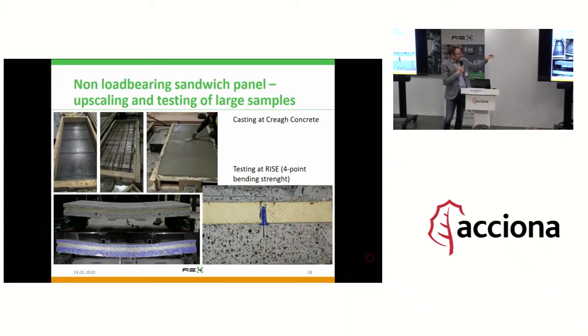And these are images from the preliminary upscaling at Creagh, in which we, from laboratory, made a first upscaling to produce test elements. And we tested this, for example, as you see down to the left, with 4-point bending strength, and supervised it with digital image correlation to see how the stress was distributed and how this element corresponded to this testing. And based on this, the real upscaling of the elements meant for the demo building was performed at the factory. To the right, you see a cross-section of the panel with insulation.